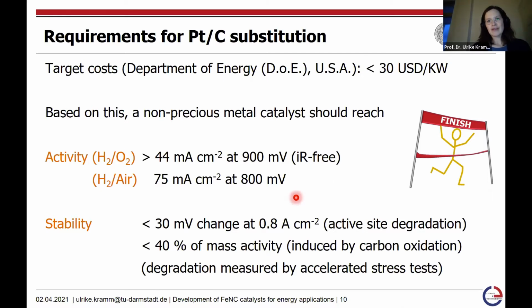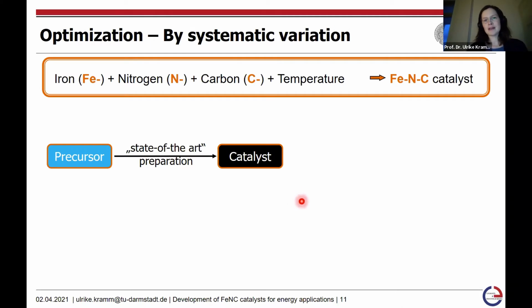For the preparation of Fe-N-C catalyst materials, it's basically like making a cake. I guess every one of you has already done so. But of course, we use different recipes and different chemicals. You can use any type of iron source, nitrogen source, and carbon source. You mix them together and then you apply a temperature program in order to form your catalyst material. Within my group, we always perform an additional acid leaching step in order to get rid of side products that might also be formed during the high temperature pyrolysis.